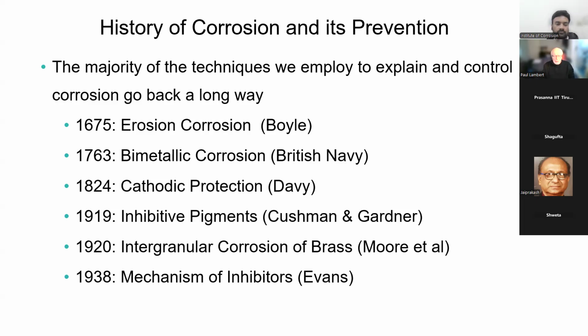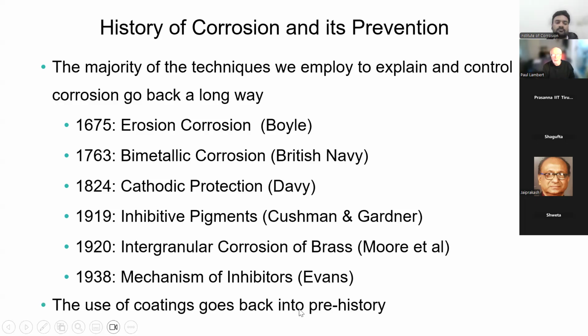Other things, intergranular corrosion of brass, famously came about by some of the wars in hotter countries, where they noticed that the shell casings of the soldiers were cracking, and it was partly the ammonia from the sweat, partly the locked-in stresses, but it was basically failure of brass because of the environment it was in. And then things like inhibitors come much, much later. The formal understanding of how corrosion inhibitors work is getting quite late on. As in everything. And that's clearly, as I say, UK-centric, but it covers quite a lot on that.